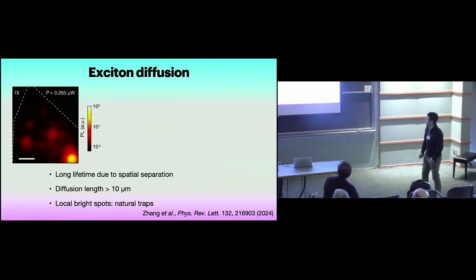So can we realize an exciton condensate? One idea is that you just keep pumping the system and create a higher and higher density of excitons. But something more interesting happens. So here I'm shining the laser over here, and the dashed line shows the boundary of my sample. You can see that not only do I create interlayer excitons over here, but also outside of my laser excitation.